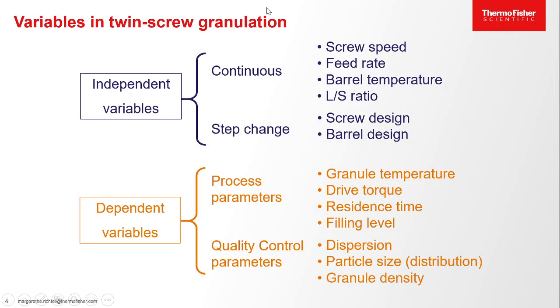The variables that change here or help you to tune your process are basically divided into independent variables and dependent variables. Independently, you can continuously change the screw speed, so how fast the screws turn. What's the feed rate, so how much throughput, how much material do I add within an hour, for example, into the extruder. Then the barrel temperature and the temperature profile, and also the liquid to solid ratio. So how much liquid do I add in order to get the granules? Then stepwise, based on disassembly and then reassembly of the setup, you can change the screw design, so the screw configuration. This is really crucial. I'll come to that later, and also the barrel design.